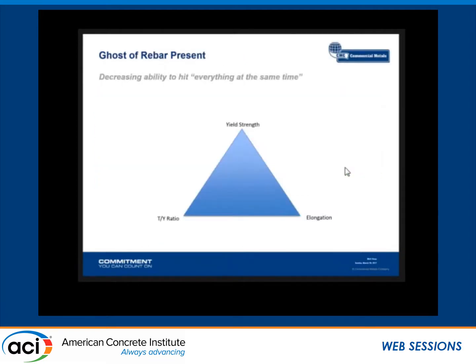Taking another look at it, this is kind of your triangle of strength. You're going to have yield strength, the ratio, and the elongation. Pick the two you want and give up the one you don't want, basically. To achieve that, you get your yield strength, you get your elongation. Microalloying and quenching will generally do that. Quenching will bring the ratio down further than microalloying, but microalloying will bring the ratio down compared to conventional strengthening.